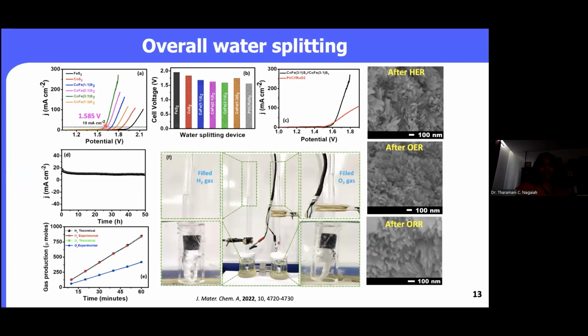And then we performed and we found that the potential at 10 milliampere per centimeter square is 1.585, compared to the other catalyst and also even compared with respect to the single metal sulfide catalyst. And the cell voltage is almost constant for the three different variants, and also it is better than the state of the art catalyst. As you can see, although the onset potential with respect to the state of the art catalyst is quite high, the current intensity is quite low.